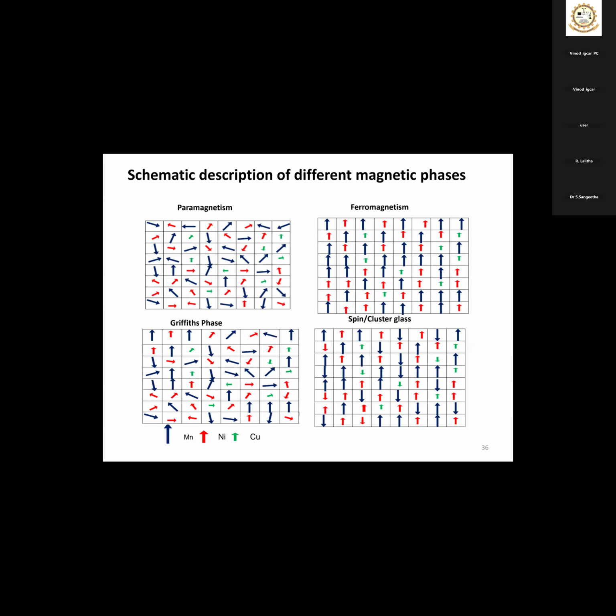Griffiths phase means it's a paramagnetic matrix. That means the main phase will be paramagnetic. In the paramagnetic matrix, there will be localized ferromagnetic components. That means localized, small, short range ordered ferromagnetic pockets are there in the large paramagnetic matrix. It is neither fully paramagnetic nor fully ferromagnetic. Long range ferromagnetic order is not developed. Only some pockets are ferromagnetic. Some short ordering is ferromagnetic.